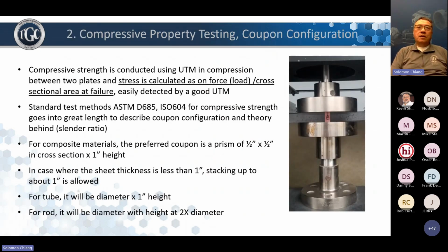And this is a picture of how we conduct compressive testing. Again, very simple. As long as you follow the rule on the sample, it should be a prism, 1/2 inch by 1/2 inch by 1 inch in length. And for tubes and rods, just follow the rule. And again, when you compare the properties of material A to material B, and it shows some compression, then you have to make sure that the properties are performed using the appropriate ASTM or IEC, ISO method. So there's an apple-to-apple comparison.